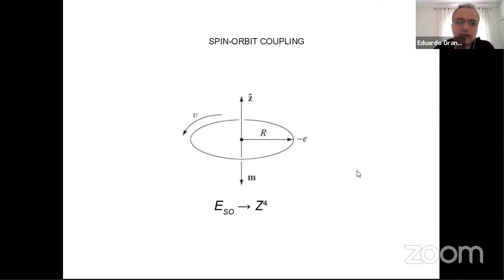So both effects together lead to a coupling with the atomic number Z to the fourth power. So when you go to heavier elements in the periodic table, you have higher Z, and the spin-orbit coupling becomes more and more important. And for high Z, it turns out that it becomes a very important interaction when you need to consider the magnetic behavior of the system.